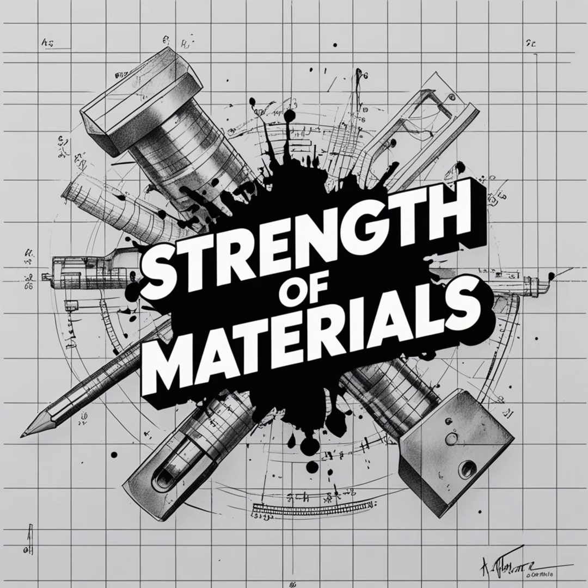Yes, and we use the exact same concept on metals. But obviously, we can't always heat and rapidly cool complex massive metal geometries like an engine block or a turbine blade the way we do flat glass. Right, that would warp everything. So we use a mechanical process. We use a brute force. It's called shot peening. I absolutely love this concept. It sounds aggressive. It literally involves bombarding a critical metal part with millions of tiny spherical media called shot, like sandblasting. But instead of cutting sand, you use little metal, glass, or ceramic balls.